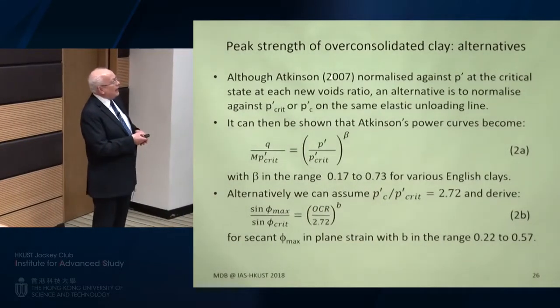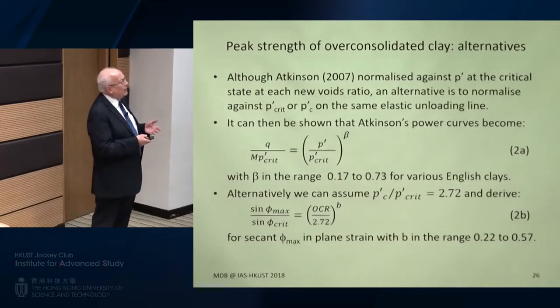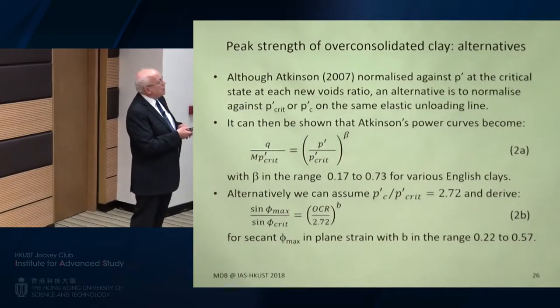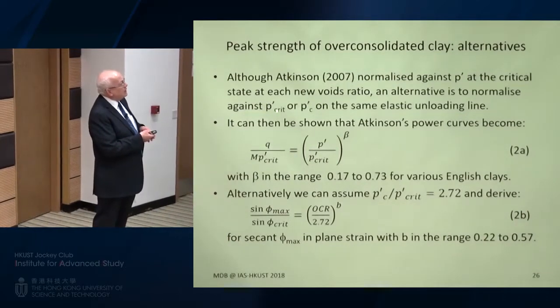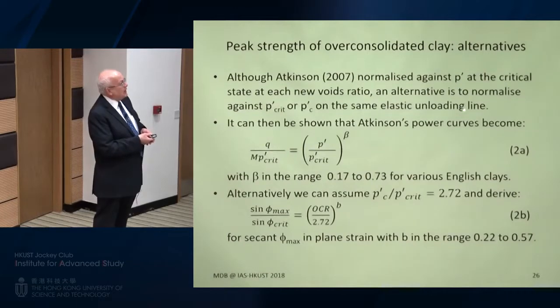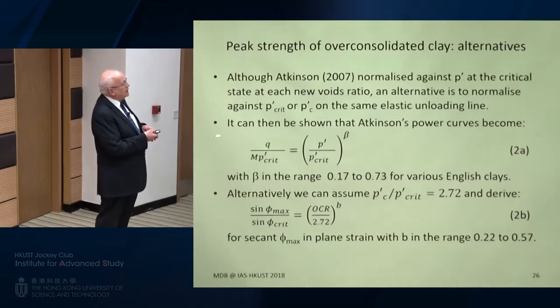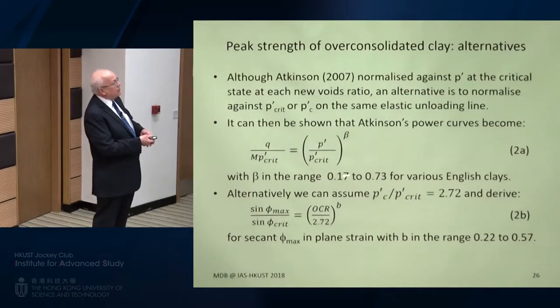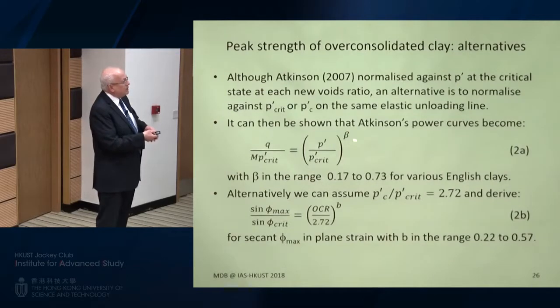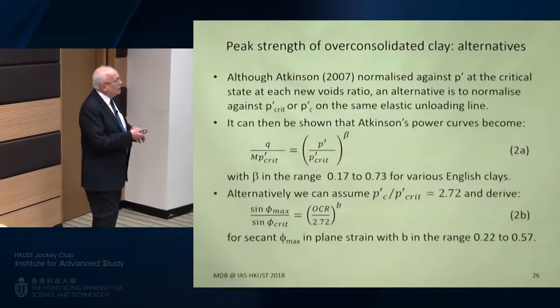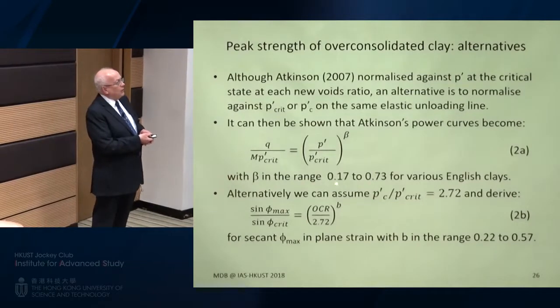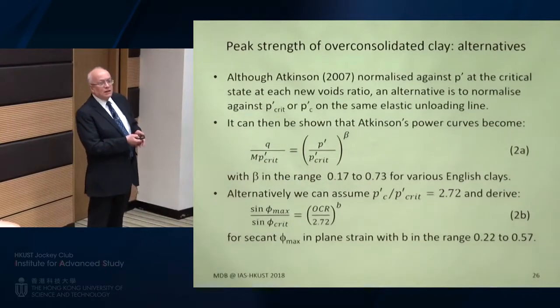Okay, so Atkinson 2007 normalized against P dash at the critical state at each new voids ratio. Well, that's a little bit clunky for what I wanted to do. So I renormalized it against P dash crit on the same elastic unloading line. And then I get very much the same equation that I showed you with the sand. And so I gave that an index beta as well. And in this case, there really was some variation from clay to clay.